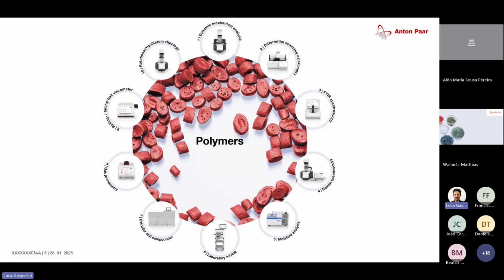So you have some sample, you put it into the sample chamber, then the instrument creates a vacuum in the sample chamber, and then we start heating up the sample. What's going to happen is that all of the volatiles and the moisture will leave the polymer matrix, but calcium hydride only reacts with water. So hydrogen will build up, and from this pressure increase, you can actually calculate the moisture, and this goes down to an accuracy of 1 ppm.